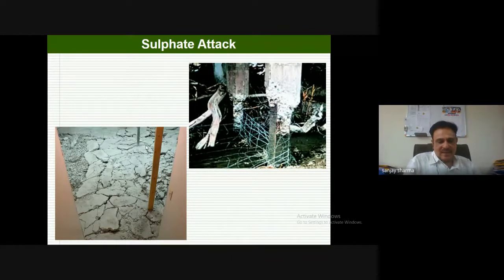So we used NDT: the rebound hammer, ultrasonic pulse velocity, and carbonation tests. What we found is that in the tank which was damaged very badly, the cover to the concrete was not proper. It was less. The other tank had the proper cover, and the quality of that concrete was good, which we found by using ultrasonic pulse velocity. So we could find out the cause of the deterioration: proper quality control was not maintained in the tank which deteriorated, and it ultimately got completely rusted, and almost the whole surface was badly damaged.